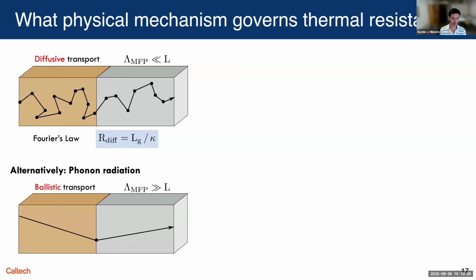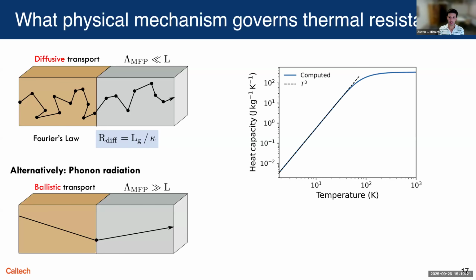But at low temperatures, phonons can propagate hundreds of microns or even millimeters without any scattering. And in that case, the transport is what's known as ballistic. The interesting thing about ballistic heat conduction is that the heat flux is proportional to the heat capacity. And if you remember your solid state physics, heat capacity goes as T cubed, the Debye law, at low temperatures. And that means that the thermal resistance, which is the inverse of that heat capacity, goes as 1 over T cubed.